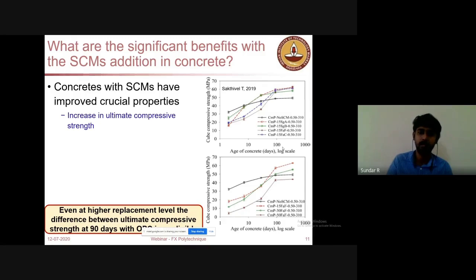necessary for your pre-stressing process and all, there might be a shortcoming. But still, when you go for a long-term assessment, concrete with SCMs outperforms OPC every time. If you see here, when the replacement level is under 30 and all, you can still see better performance with fly ash addition or even slag addition than OPC at 90 days or at more than 1 year strength. If you see, OPC has a lower ultimate strength than this Portland pozzolana cement.